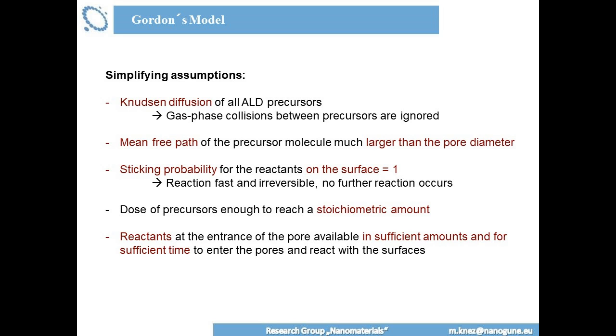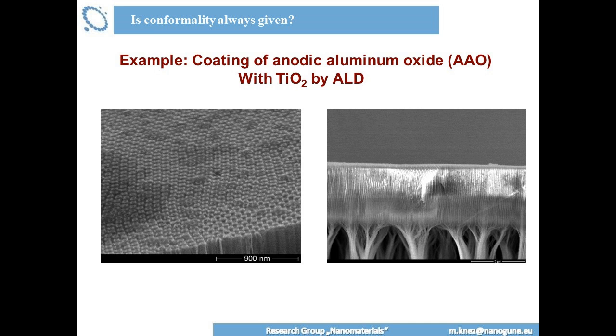Now here, if you don't have experience with ALD and the dosing, you really need to think a little bit about the surface that you have. People sometimes tend to underestimate the surface area which they have in their chambers upon coating. Imagine you have such a porous aluminum oxide, which I showed before. This kind of thing here. A small chip, depending on the pore size, of course, that you etch here. A small chip of, let's say, 1 centimeter diameter and 50 micrometers depth can easily have several tens of square meters surface area, depending on the pore diameter. So don't underestimate the surface that you have here for coating.